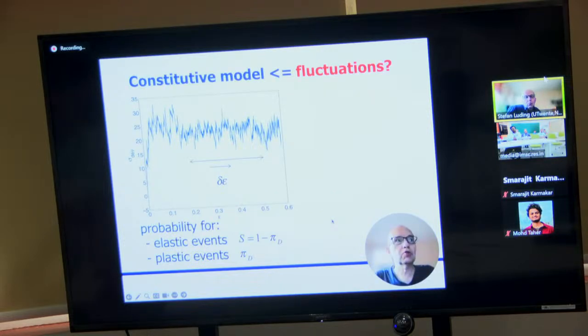Consider shear stress versus shear strain. The blue line is shear from an isotropic state during a certain time with a relatively slow rate. Now, what happens during shear is that you have elastic regimes and you have plastic events. So there's a mix between elasticity and plasticity. In this resolution, you cannot see it. I will zoom in on the data.